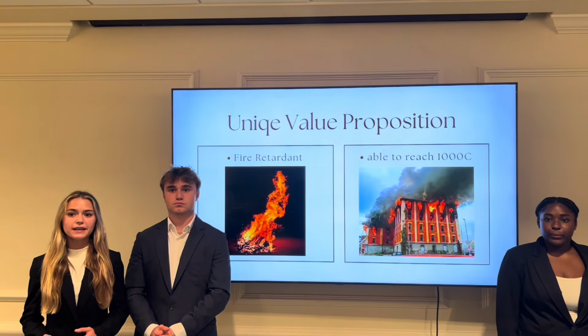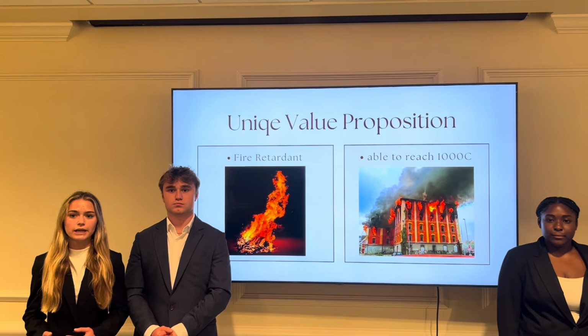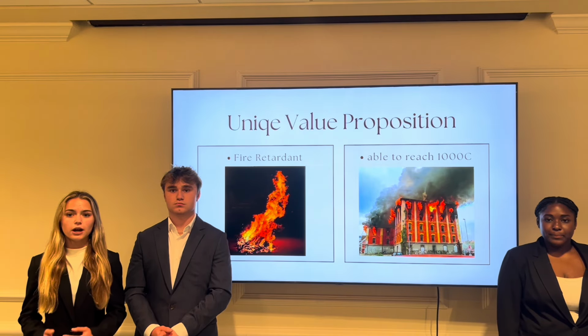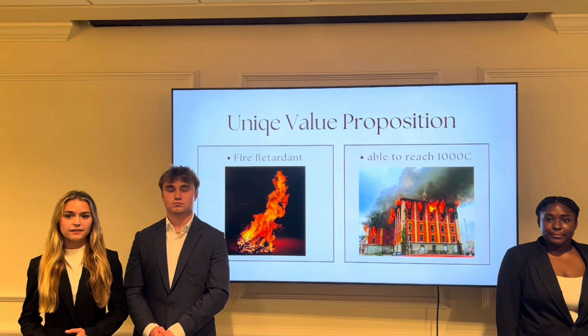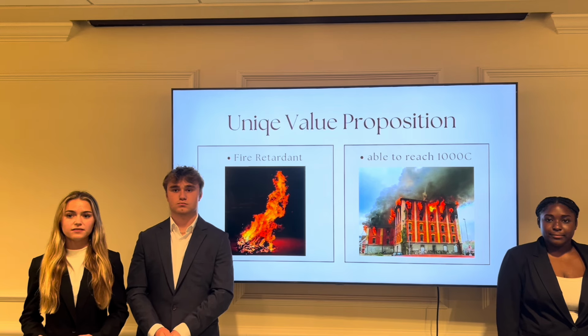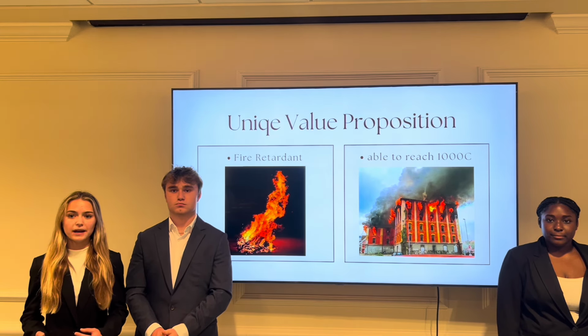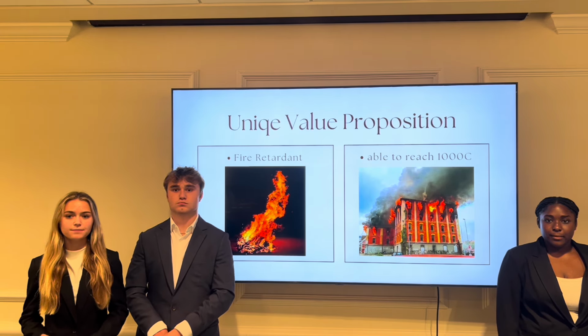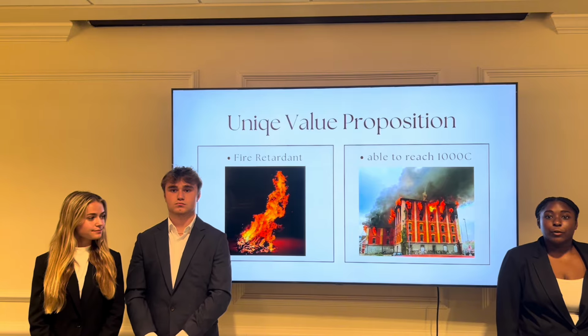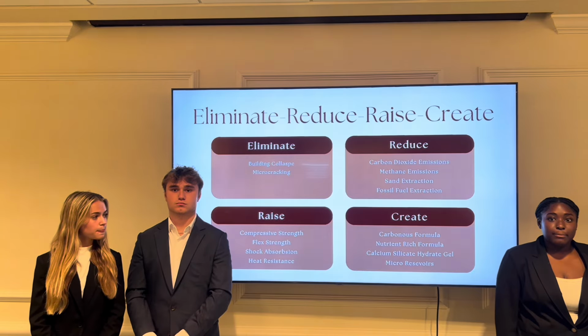Extreme heat rapidly increases the internal temperature of concrete, weakening steel rebar. Biochar absorbs water, slowing the temperature rise. When exposed to 1,000 degrees Celsius, biochar concrete retains compressive strength compared to standard concrete. CarboCrete eliminates structural vulnerabilities, preventing collapses like Surfside.